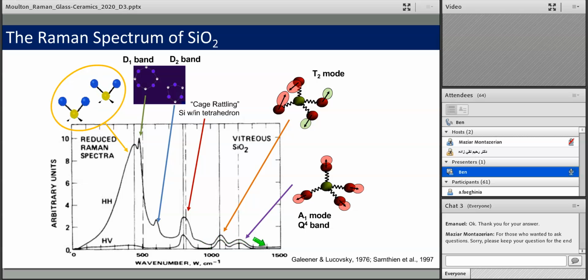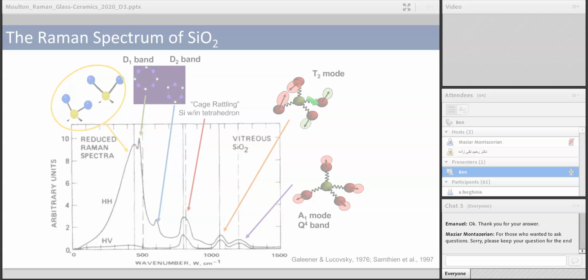Above 1,000 wave numbers, we have two broad, low-intensity peaks that are assigned to the T2 mode. And in this, the tetrahedron has opposite edges. Here's one edge, here's the opposite edge, that compress and expand inversely related to the other. So one expands and one compresses. And this is related to those Q4 species in the network that we were describing earlier.